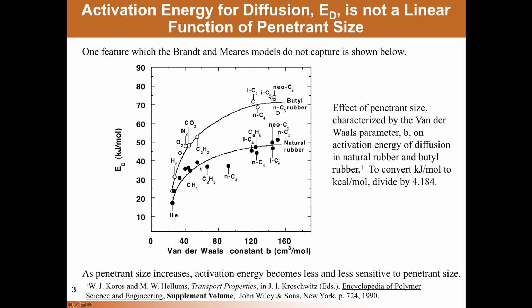increasing and then plateauing as you get to large penetrants. That is, over here, as you go from helium up through the light gases and some of the light hydrocarbons, there's a strong increase in activation energy of diffusion with increasing size of the penetrant as characterized by this van der Waals constant. And then beyond a certain value, the activation energy of diffusion doesn't change very much, even as the penetrants get much larger. And this has led to